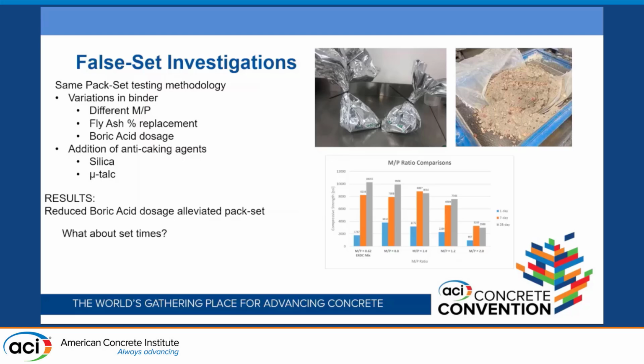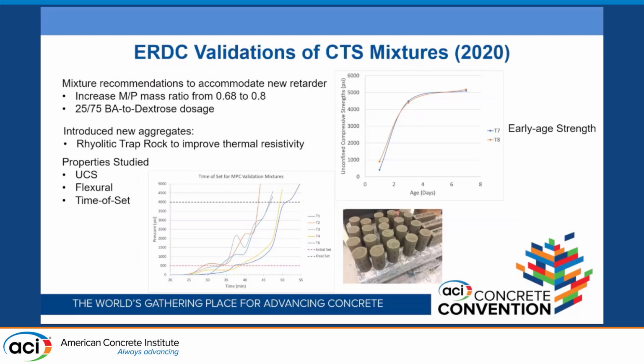And so where do we go from here? They actually came up with dextrose, another sugar. And they did a dextrose combination with the boric acid of 25% boric acid, 75% dextrose. They did a few iterations of this, but long story short, with the dextrose boric acid combination they maintained performance. Pack set was no longer an issue. And then this plot over here is our strength results from those mixes.